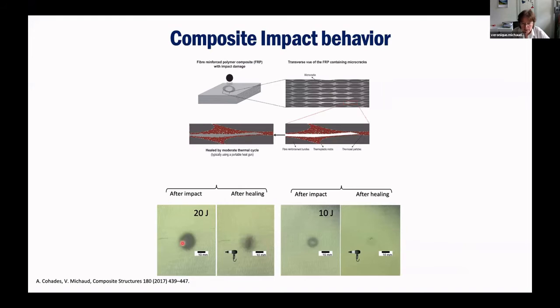And after impact, we see that, of course, there is a big damage, and using glass fibers is great because you can see through. And then after healing, we see that at the impact of 20 joules, we have a reduction in the damage zone, but it's still visible. After 10 joules, we had a damage zone here, and after healing, we barely see the damage.